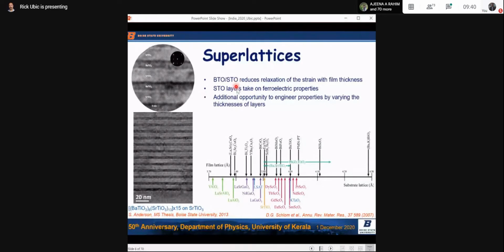And when you put them together, because they're different materials, barium is much bigger than strontium, you have different strains, and you can relieve some of the strain in the layers by alternating the materials like this in these stacks. And it also means you put some strain into the strontium and you make it ferroelectric as well. So there's all sorts of opportunities to engineer properties by varying the thicknesses and the frequency of these layers. They look like this. So that's one sort of superlattice engineering application of this sort of modeling work.